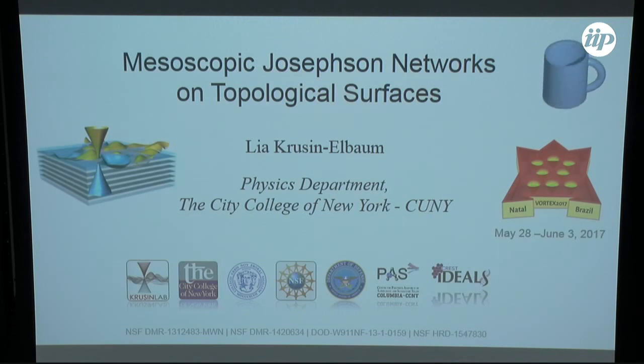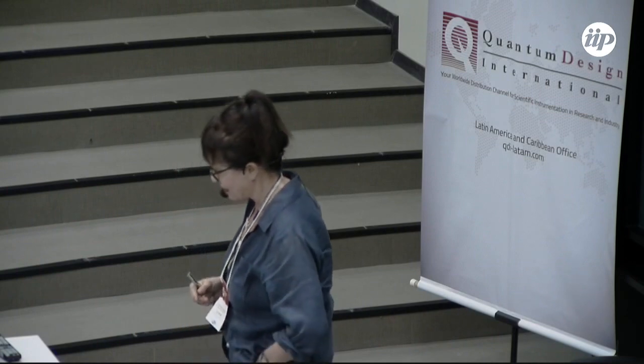Can I move this a little bit? And today I will show you that actually, as always by serendipity, that's my way of doing things, we found remarkable low energy modes in the superconducting system that seem to be surface modes and perhaps are related to something that is topological. And I will not be stronger than that because this is still somewhat unusual, and certainly there is no theory of that, so a lot of speculation. I would invite you, as experts on Josephson junctions, especially in systems with unusual order parameters, to come to me with some ideas that may explain that.